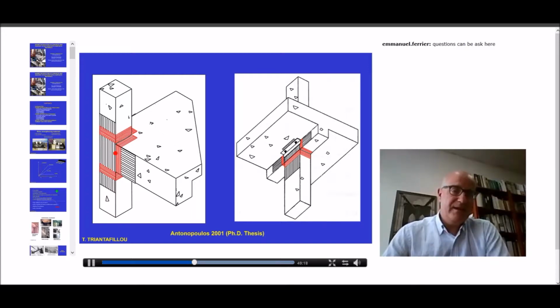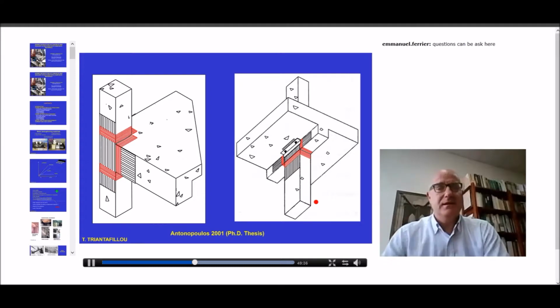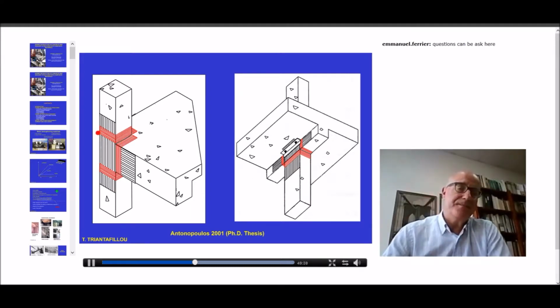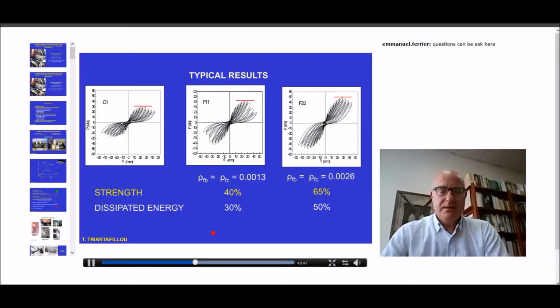To make sure that they would work inside the joint panel, those fabrics should be anchored outside the joint area. For example, by using those transverse FRP tapes or maybe metallic anchors or any kind of anchorage system you can imagine. The idea is to make sure that the fabrics are anchored beyond the joint area. Typical results of the response of joints. This is a control specimen without any retrofitting, so you see the shear force in the joint versus a measure of displacement.